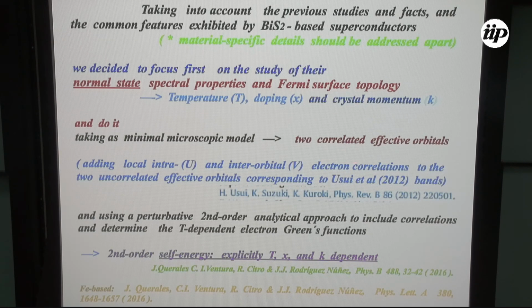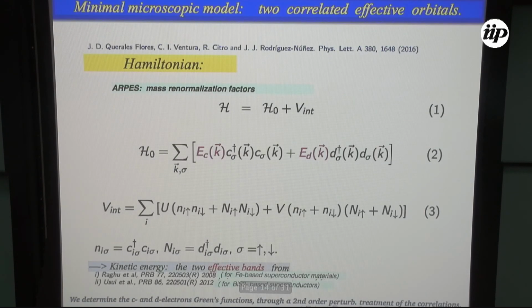And we could determine, as I will briefly mention, perturbatively the second order temperature-dependent electron Green function for these two effective orbitals. From there, we got the self-energy, and from there we can, of course, start looking at the spectral function and compare with ARPES results. And we also, I'll just mention what we did for the transport. But in principle, what we did was that, starting from those bands, add correlations in this way.